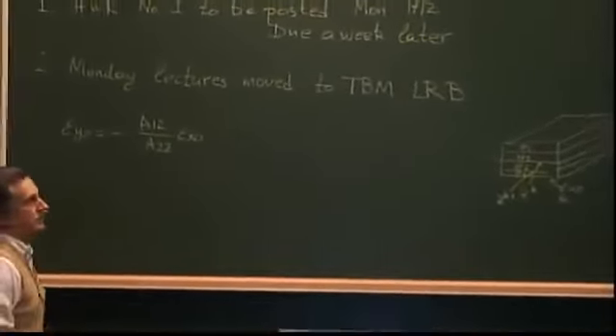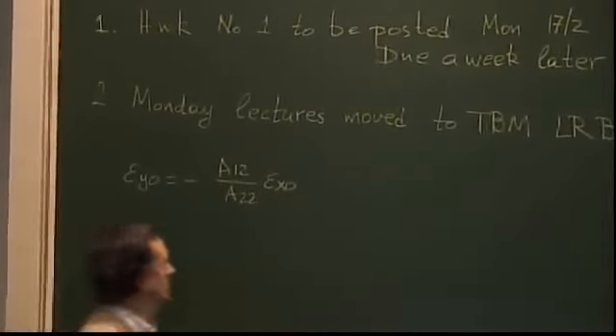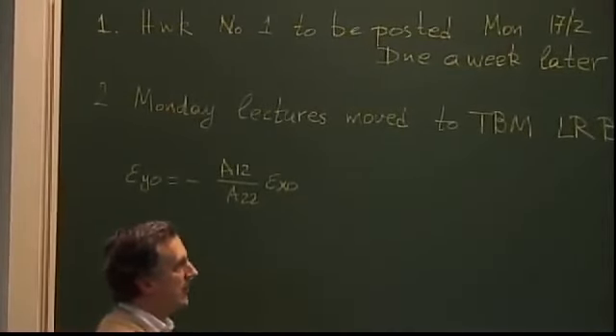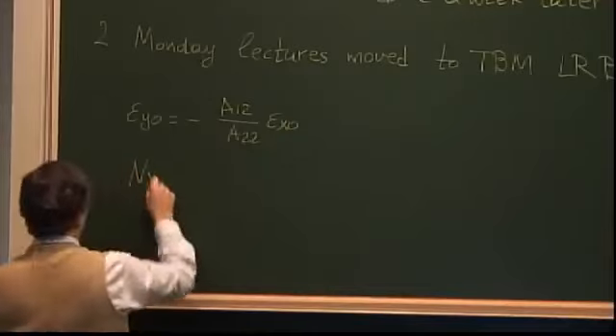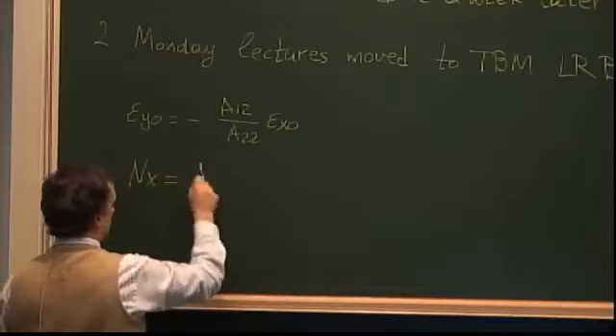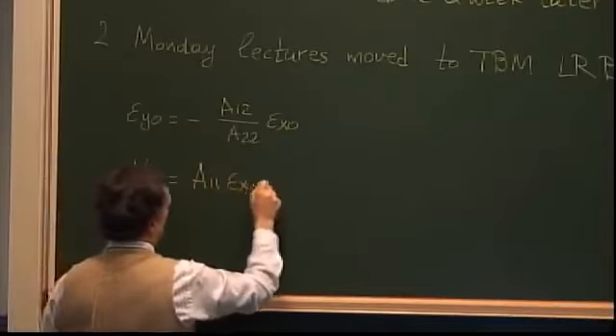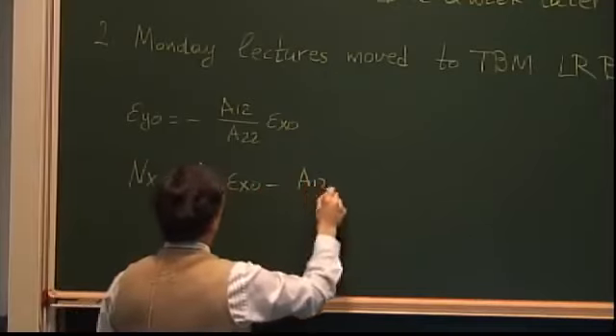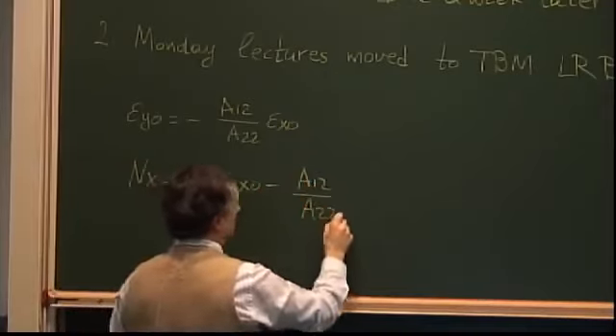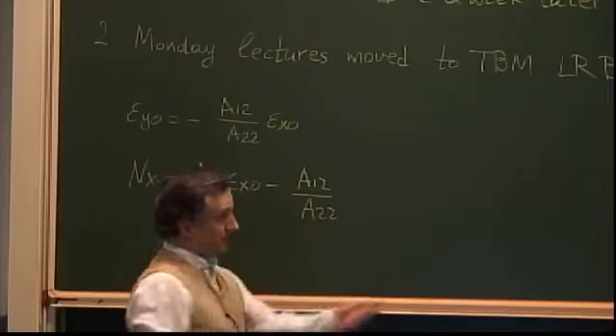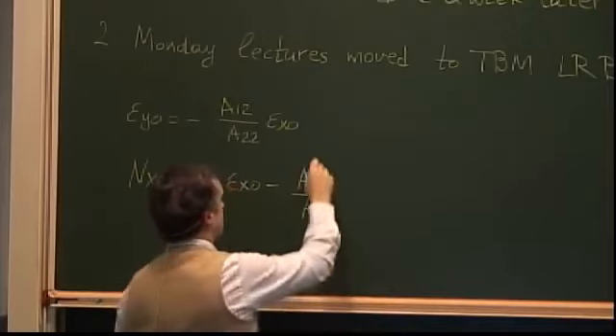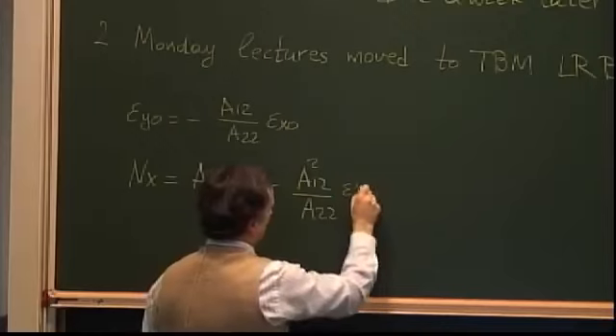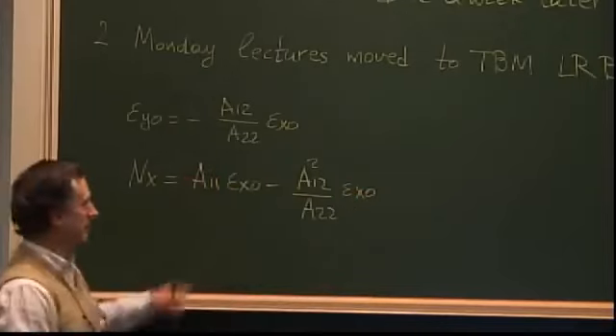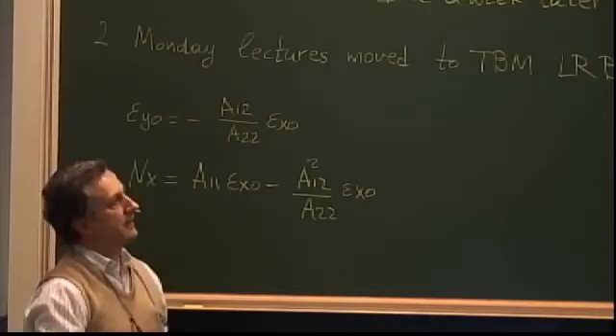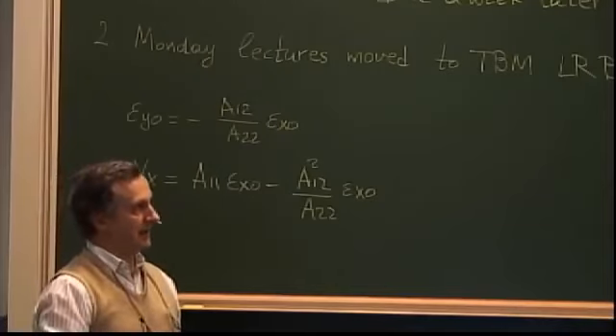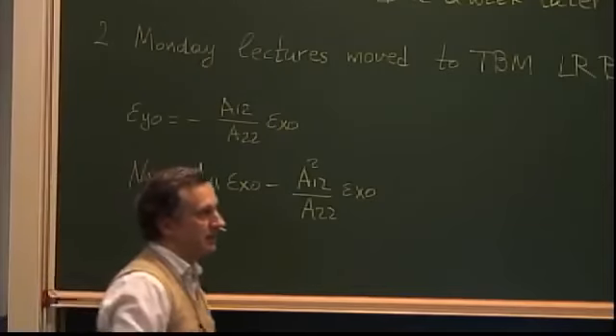I get this, which I can now substitute into the first equation where epsilon y0 is, to get Nx is A11 epsilon x0 minus A12 over A22 times another A12 that we have over there. So that's A12 squared epsilon x0. So if I factor out my epsilon x0, I arrive at the equation here in the middle that relates the Nx with the epsilon x0.